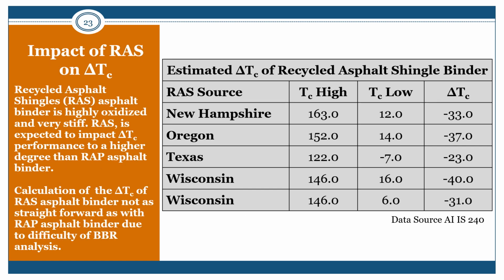This table presents estimated delta TC data from RAS binders from the National Center for Asphalt Technology NCAT report 1601, as reported in TRB E-Circular 241 and additional data from the Asphalt Institute IS-240. RAS asphalt binder is highly oxidized and very stiff. Therefore, RAS is expected to impact delta TC to a higher degree than experienced with RAP asphalt binders.